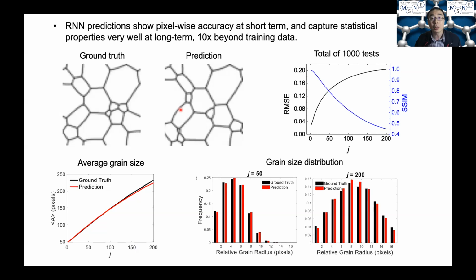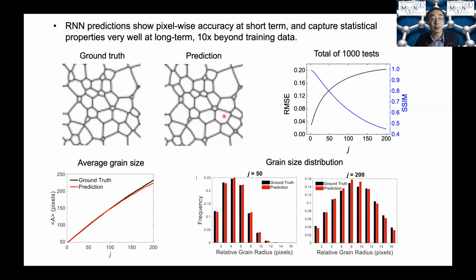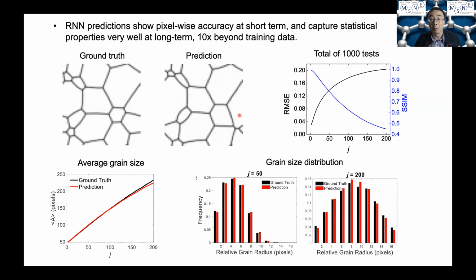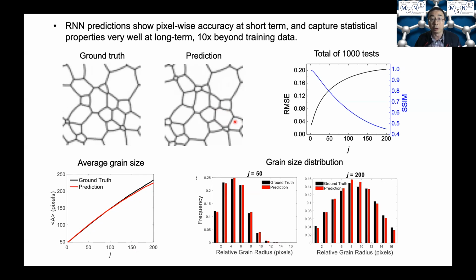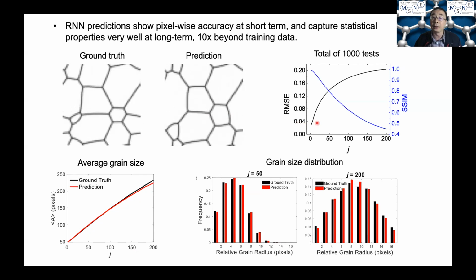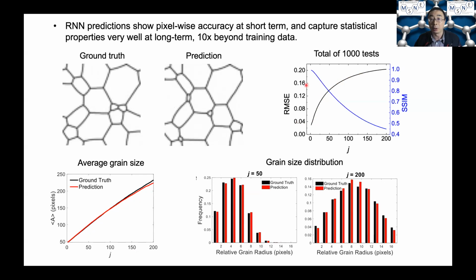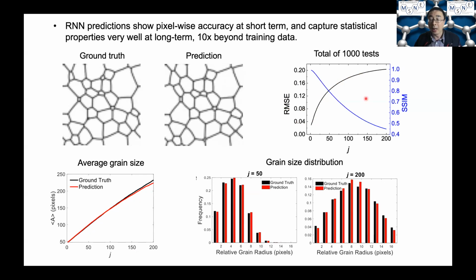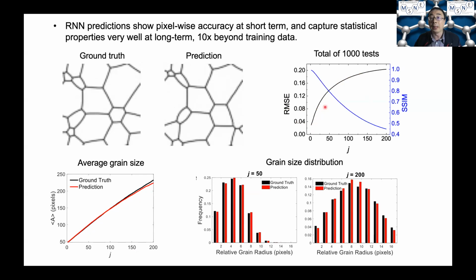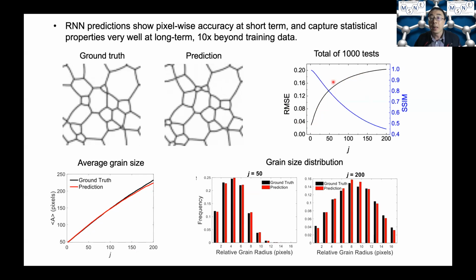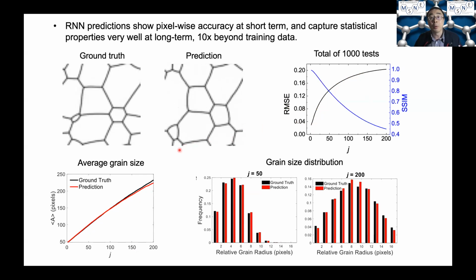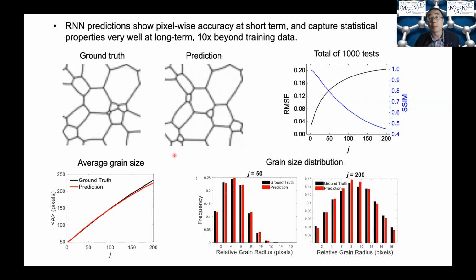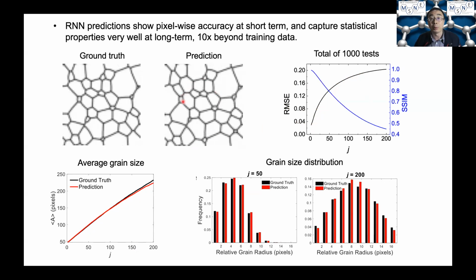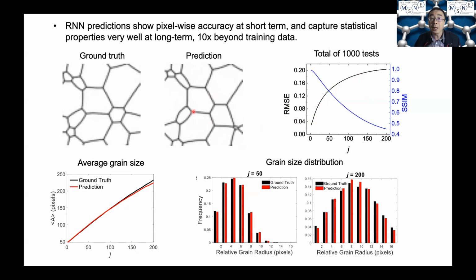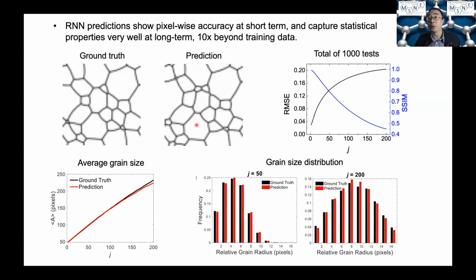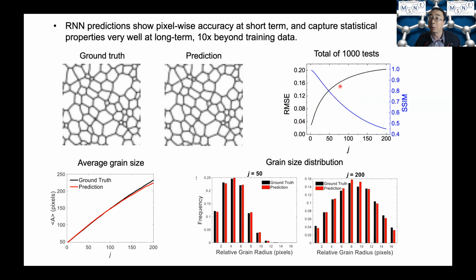Right? But when time goes on at a later stage, we do notice there is some visible difference between these two in local regions. And this is also reflected in the pixel-wise comparison, such as RMSE and SSIM. You see the error gradually increase with the frame number. But I want to highlight that when you look at the statistical properties of the microstructure predicted by the RNN model, it actually has a much better performance than the pixel-wise comparison implies.